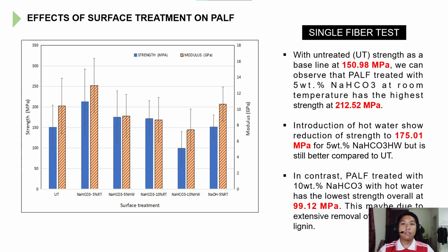But at 10% of sodium bicarbonate with hot water, that has resulted in the lowest strength compared to all the other results. This shows that alkaline treatment is able to remove impurities, and with the removal of these impurities, it can increase the strength of the fiber. However, if we remove too many impurities, it could cause degradation and could lower the structural integrity of the fiber itself.